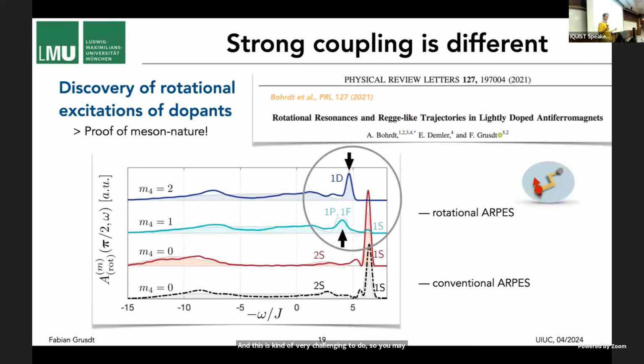But once we put angular momentum into the system and create a hole that has angular momentum, going around its spin excitation, we can see a completely new peak appearing. With different angular momentum, it's basically here, and it's clearly above the ground state peak that we usually observe. This means, beyond doubt, at least in the small t-J model, that there's a long-lived rotational excitation in the system that we can look at.